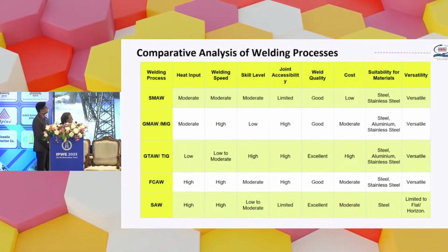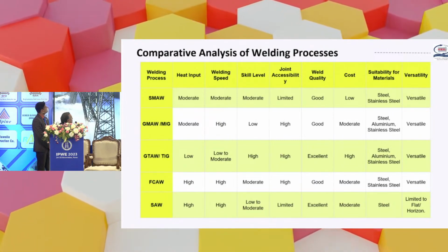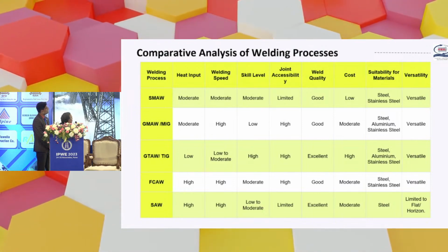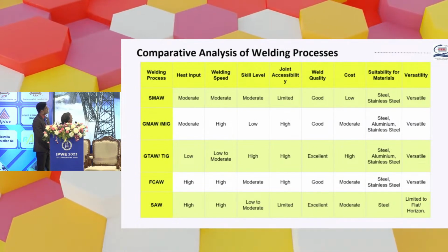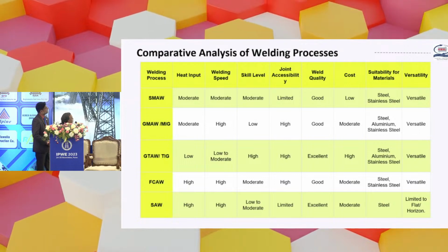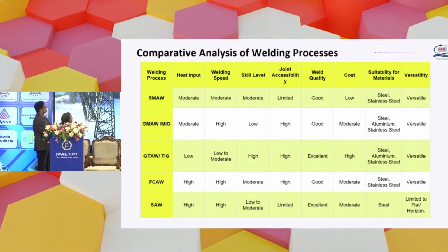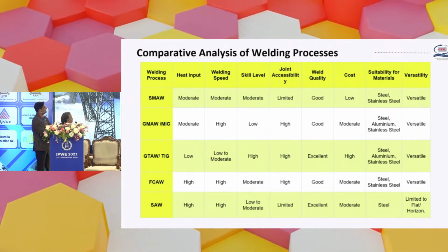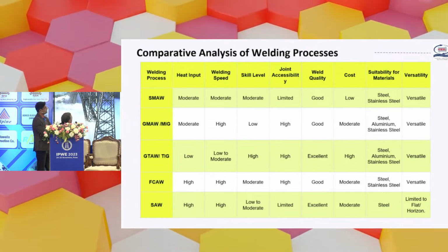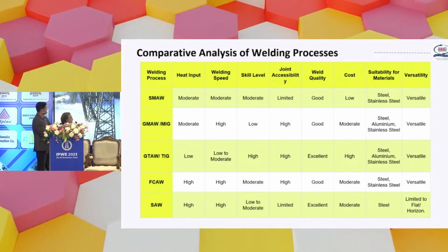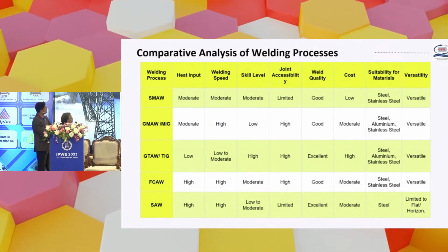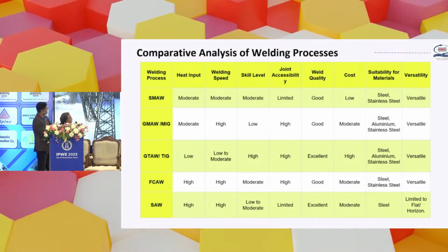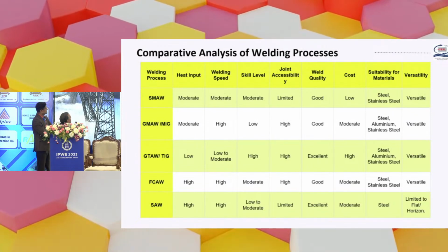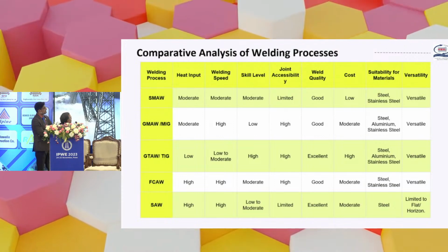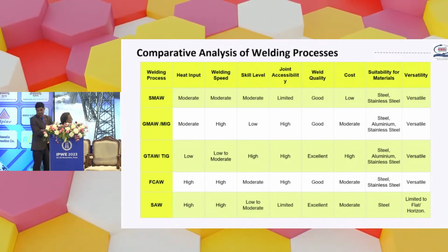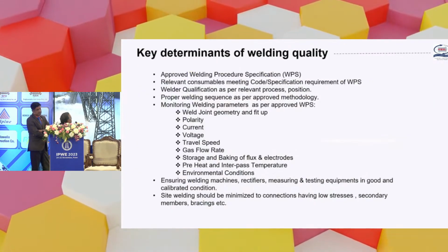SAW welding is limited to the flat position, but it has the advantage that high speed and good weldability can be achieved. But depending on the geometry of the component, due to the portability of FCAW and GMAW, where SAW cannot be used, those welding processes can be used. And SMAW, where non-critical items like handrails can be welded by this process.